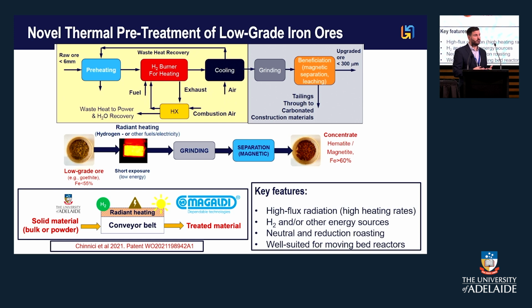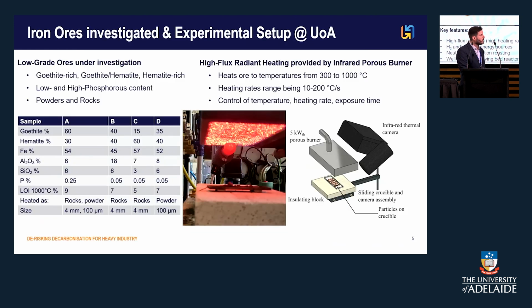As I said before, the high flux radiation can come from different energy sources. We have strong insight at the moment into hydrogen combustion, but as you see from the drawing there, this can also be provided from concentrated solar thermal energy, resistive heating, or hybrids of those. The other point of distinction is that this can be provided in either a calcining or a reducing environment, depending on the type of iron concentrates that you want.